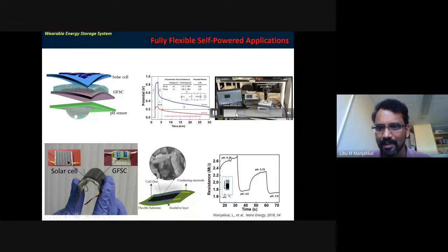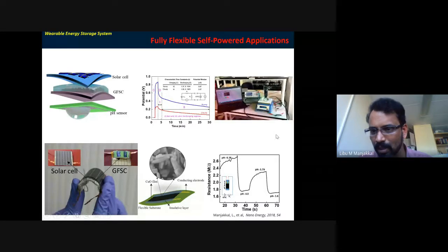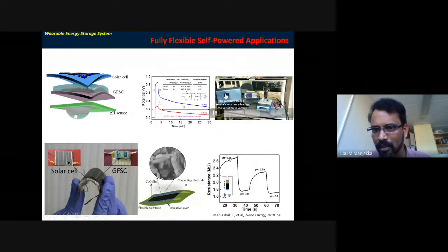And then finally, I integrated the device, like you can see here, and I measured solar cell properties also. And then I applied it for a pH sensor. You can see in the bottom figure where I used a pH sensor operated by the graphene foam based supercapacitor. This work I published in Nano Energy, and if you need more details, you can find them from here. You can see there is a sensor inside the beaker, and on the table the green one is a supercapacitor, powering and operating the sensor.